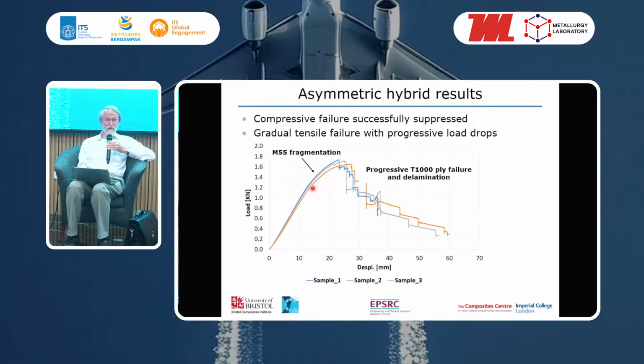So what we saw was fragmentation of the M55 on the tension side, a change in slope, and then eventually we get to the point of failing the first T1000 on the tension side, get a bit of a load drop, go a bit further, fail the next T1000, a bit of a load drop, and we get multiple failures with the T1000 through the thickness, followed by local delamination. And gradual failure and gradual drop in the load all the way down to this point here.